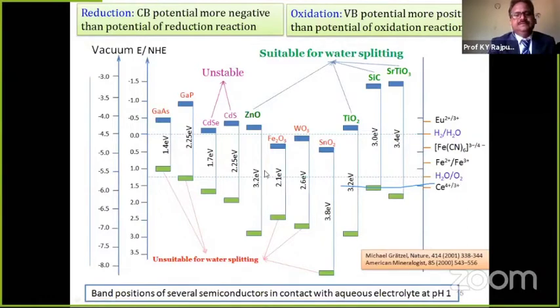But here you can see materials like gallium arsenide, gallium phosphide, cadmium sulfide, cadmium selenide, iron oxide, tungsten trioxide, tin oxide, are not suitable for water splitting due to their band positions. And CdS and CdSe are unstable. So the materials which we can use are titanium oxide, silicon carbide, and strontium titanate, and other oxides if we tailor their band edges.